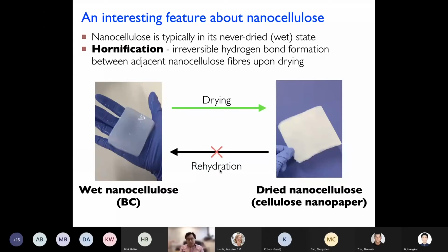An interesting feature of nanocellulose is this thing called hornification. Most common materials, when you dry them, you remove water, you produce a dry cake, powdery materials, which you then dump into water again. You should be able to redisperse them in water. Cellulose from paper works up to a certain extent. Nanocellulose is very, very difficult to achieve that reversibility in redispersion. So here's a picture that demonstrates that.